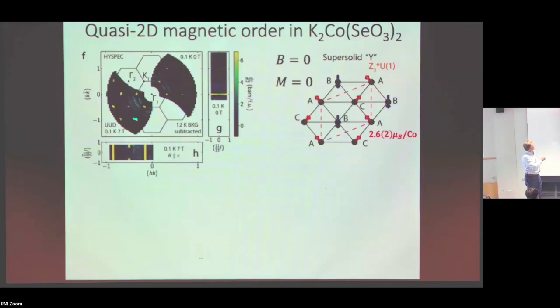Okay, so what happens when I come to a field? So I put 7 Tesla on. Now I get the little dot in the middle. And so that means that I have magnetized the system, as we expect. And interestingly, I still have lines of scattering along these outer peaks, still rods of scattering. But the peak in the middle, which we call the ferromagnetic peak, that one is a proper and full Bragg peak. It's just dots. And so that is because I have magnetized the whole crystalline structure as a periodic crystalline unit. And so it becomes a full-out Bragg peak.